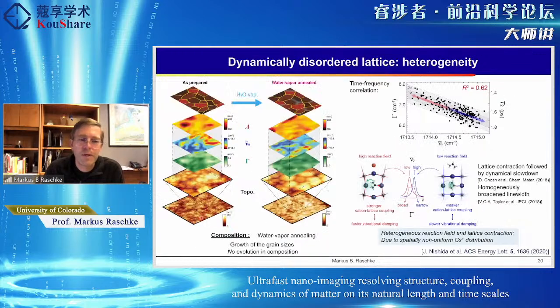So here's an example how these measurements are performed. We do atomic force microscopy overview imaging. Then we'll zoom in into a smaller scale of these different granules from this polycrystalline structure of these films. And then we analyze line widths and peak position, and then correlate with some of these topographic features and these grains. And then we'll, of course, study intragrain and intergrain heterogeneity. And then we can modify the film, for example, in water vapor annealing. Then you actually see, as a result of this highly flexible structure and a lot of diffusive processes, that these polycrystalline grains grow. And so we get sort of a ripening process, and then we can continue to monitor how this affects then the lattice.